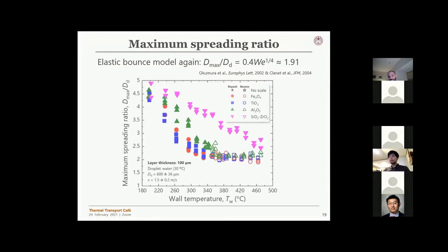Also, if I plot the maximum spreading ratio, which is the maximum spreading diameter divided by the initial diameter of the droplet, we have this nice curve here, but still the transition from film boiling regime or bouncing regime or deposition regime is not very consistent among these oxide layers.